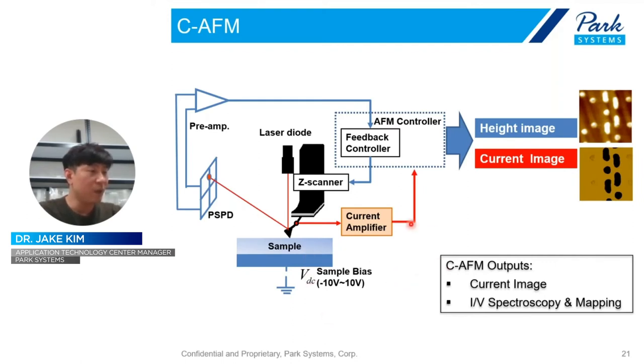And the concept of conductive AFM is also quite simple. The same as the contact mode, the tip contacts the sample surface and scans. But the different thing is that we connect the current amplifier and apply the bias. Then we can see the contact mode height image together with the current image.